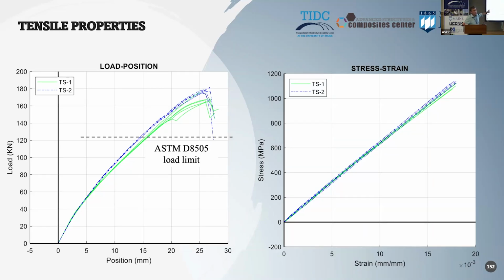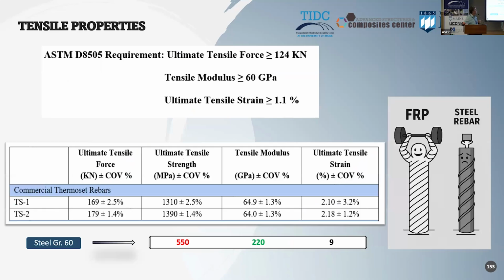We extract the first portion of the curve and we measure there the modulus by looking at the stress strain. Next one. Now we go and compare with the requirements for the standard. They're given there. There's a minimal tensile force. There's a minimum modulus. That's key, that modulus. 60 gigapascal. There's a minimum tensile strain. Both materials pass this very well.